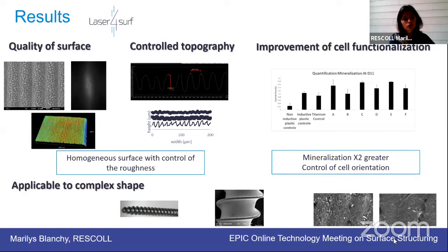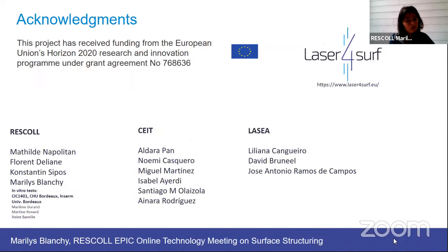And finally, we also worked on 3D shaped products. Here, this is a screw, for example. We can see that we were able to functionalize and to have a specific area of the texturing, which means that we can fine-tune the texturing on the surface of the implants. So to conclude, laser texturing is a very promising method for surface treatment to obtain fine-tuned surface parameters according to the specifications we want to reach, to treat complex surfaces and to have no chemical modifications of the surface. I would like to thank you for your attention, and this is an acknowledgement of the project. I don't know if you have any questions.